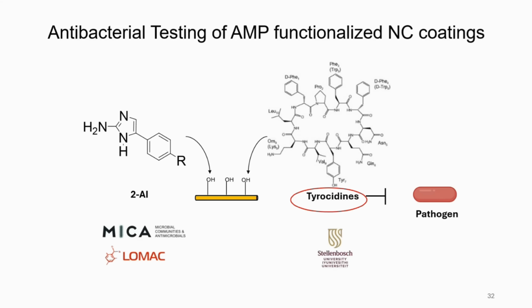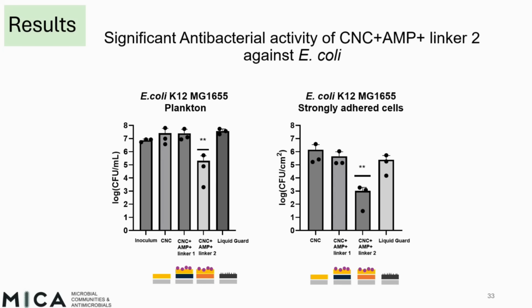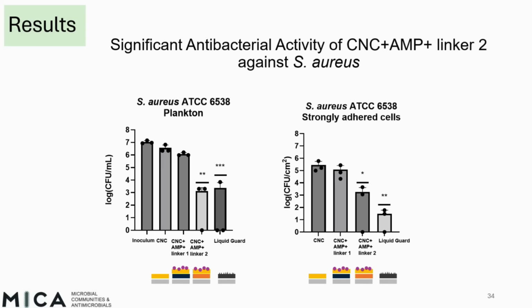Then we evaluated the activity of nanocellulose modified with the tyrocidines, also coated on glass, against these pathogens. Here we tested CNC coated on glass, CNC modified with the AMP with linker 1, CNC modified with the AMP with linker 2, also both coated on glass, and we also compared to a commercially available antimicrobial surface, which is called Liquid Guard. And here we could see a significant decrease in planktonic and strongly adhered cell counts on the CNC modified with the AMP with linker 2, and we didn't see this activity for CNC modified with the AMP with linker 1. And the results were also consistent against Staphylococcus aureus, where we only saw significant decrease in cell counts for CNC modified with the AMP with linker 2.